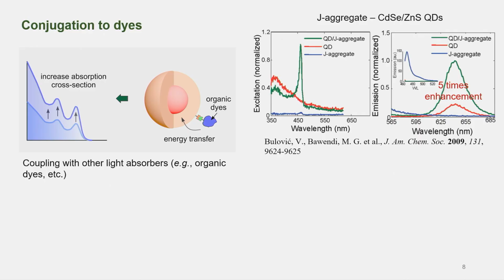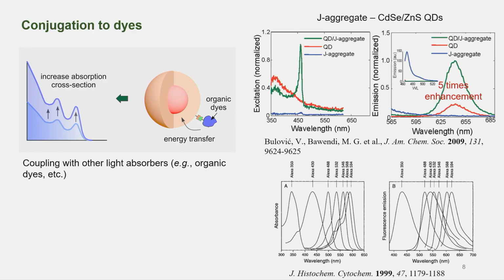You can see a sharp increase in effective absorbance of light by the J aggregates, and if you excite the quantum dots or the whole system around this range, you can get 5 times enhancement of the PL, which is caused by the enhanced absorption. You may argue that this is very narrow, and we do want a broader absorption band across the whole blue range. So we can take advantage of the well-developed organic dye field. There are a lot of dyes designed and synthesized that can cover a large area of the blue range and emit in the blue range as well.